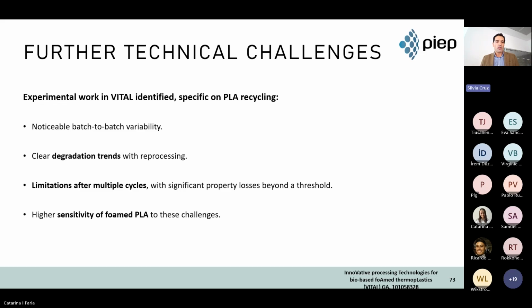Of course, we identified some limitations after these multiple cycles. For sure, if we add a lower percentage of recycled material to a virgin material, we get better results. But at least we know that these variations are massive. And of course, we also observed, because we compared the non-foamed with the foamed material, that the sensitivity of the PLA foamed materials is higher than the non-foamed.